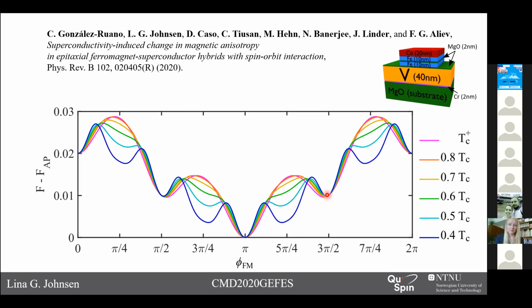But for lower temperature, when you're in the superconducting state, the magnetization will instead be trapped in this minimum at 5 pi/4. And this is exactly this pi/4 rotation that we saw in our theoretical prediction. If you're more interested in these experimental results, I encourage you to see the pre-recorded talk by Cesar González Ruano, who was the first author of this paper, and this is contributed to this mini colloquium.